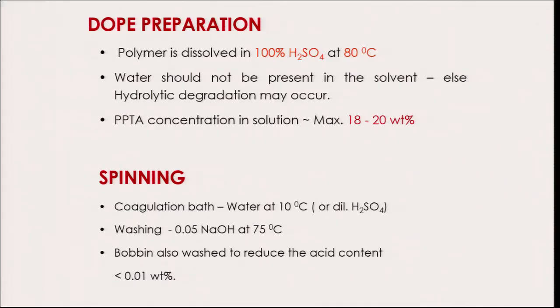The polymer is dissolved in sulfuric acid at 80 degrees, and the point to note is the water should be absent. It is 100% sulfuric acid. Water cannot be tolerated. If water is there, it would lead to hydrolytic degradation at this high temperature. The PPTA concentration, as I showed you on the graph also, is about 18 to 20% is the most desirable, right. And using this solution, I can carry out the spinning like I do it for the normal acrylic fiber. I use a coagulation bath.